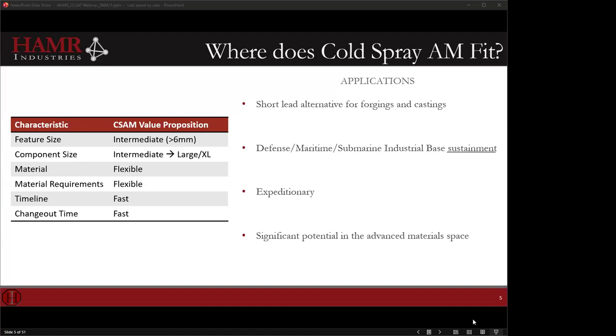The material is flexible. This is an advantage. We'll talk about this throughout the discussion today, but the materials that cold spray can do are traditional manufacturing alloys. So we don't have to do a material swap. So when we look at qualification and the challenges that are there, having a material swap and a process swap can sometimes be doubling your difficulty. And it's also amenable to non-standard materials. And then the requirements for those materials are also flexible. So in terms of particle size, morphology, shape, in cold spray, we in fact sometimes like a powder that is not spherical. So water atomized, more economical powders. We've utilized mechanical powders.